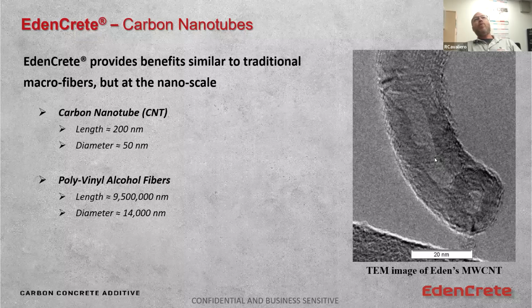A carbon nanotube that is put into a cement paste matrix provides benefits that are commonly provided in concrete using traditional macro fibers, microfibers, structural fibers. But we're doing this on a much smaller scale, right? The nano scale. So carbon nanotubes on average are a length of 200 nanometers and a diameter of 50. We produce a bell-shaped distribution of lengths and diameters. And there's a purpose for that.